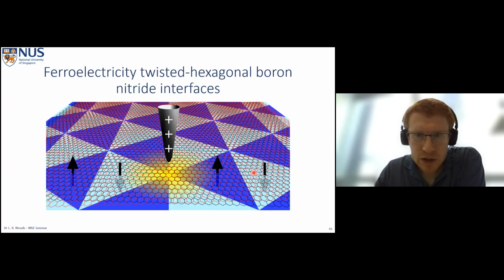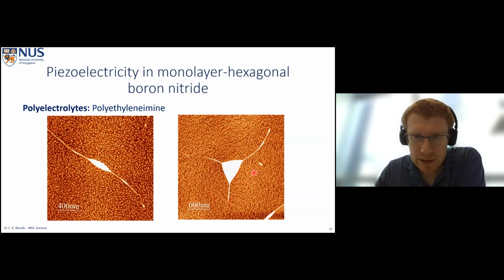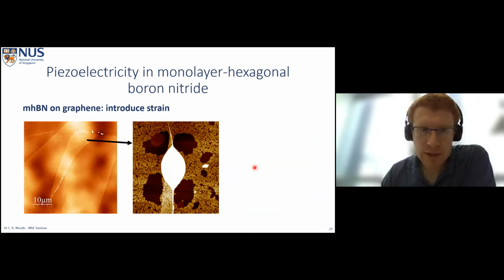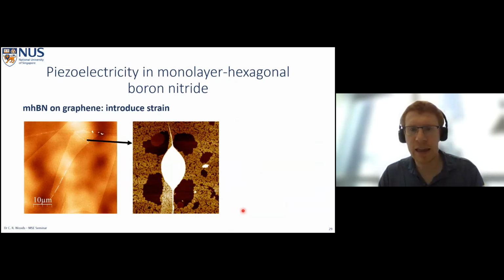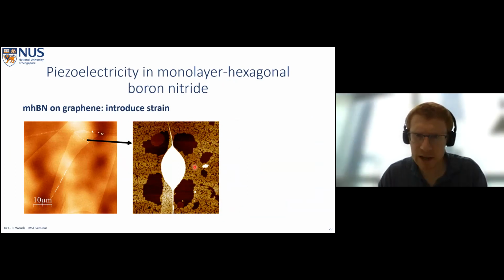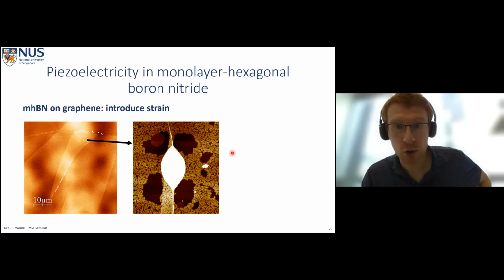So the motivation is twofold, really. One is coincidence, and one is that, as you say, these are nice systems to look at. Let me return to this image here. This is maybe the first indication we had that piezoelectricity here would be a nice thing to look at. It was an incidental thing. We saw this contamination form all around this bubble in one of our monolayer boron nitride samples. And the effect is so strange, and I can't really do justice to the fact that when you look across this sample, you see this for all of the bubbles. You can see for this big bubble here that we have contamination related to the bubble, but you can also see a little bubble where we see the same thing coming out from the edge. And this gave us an indication that maybe there's quite a strong effect here.